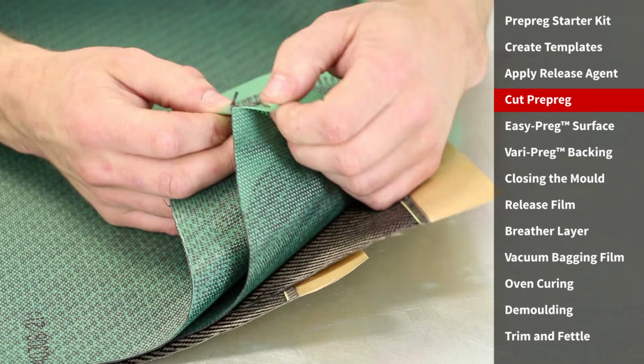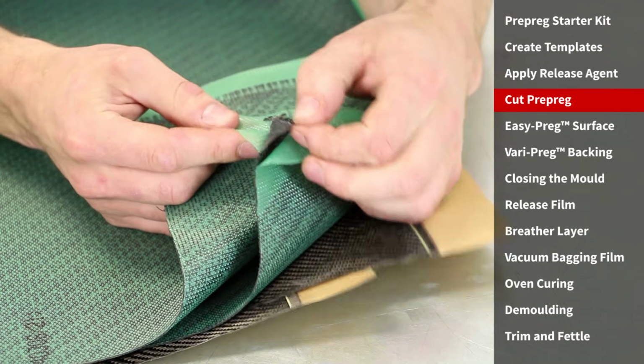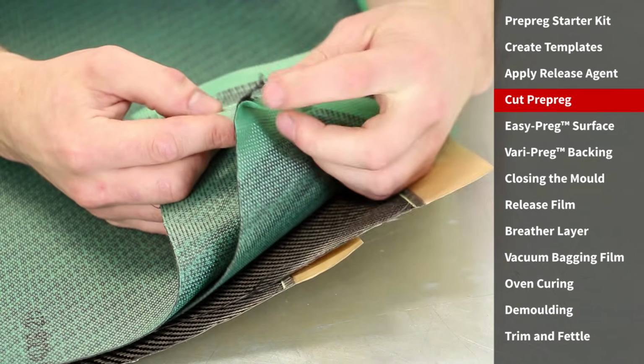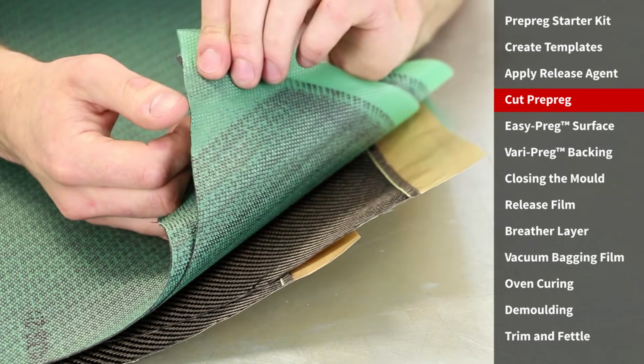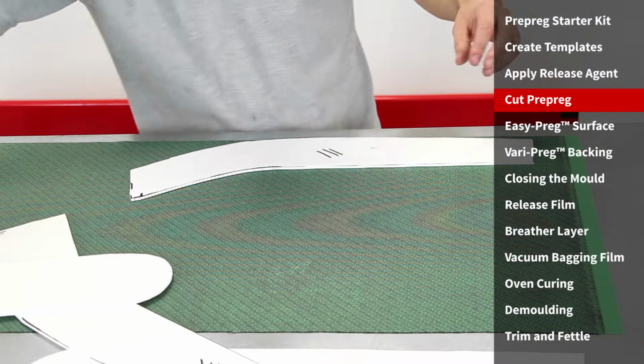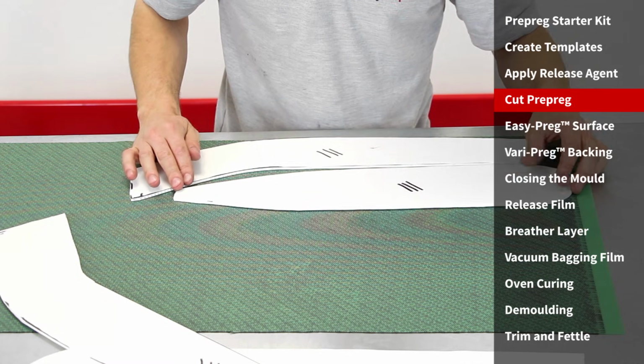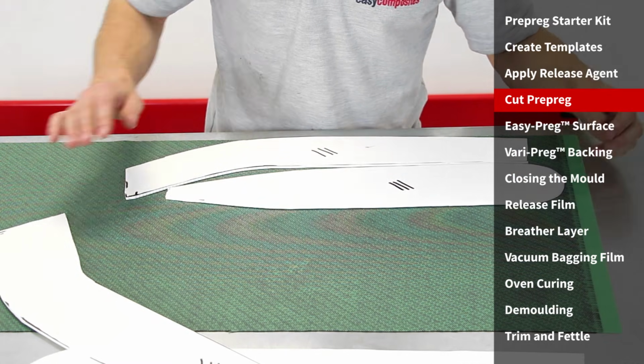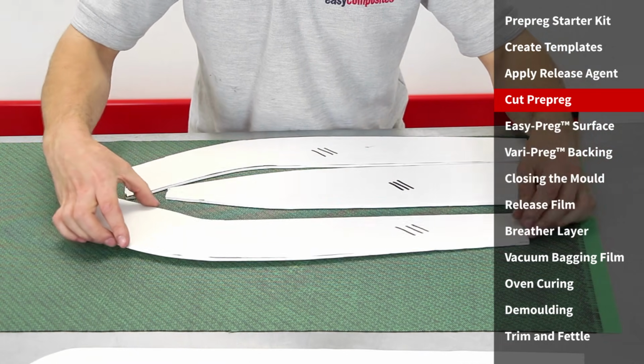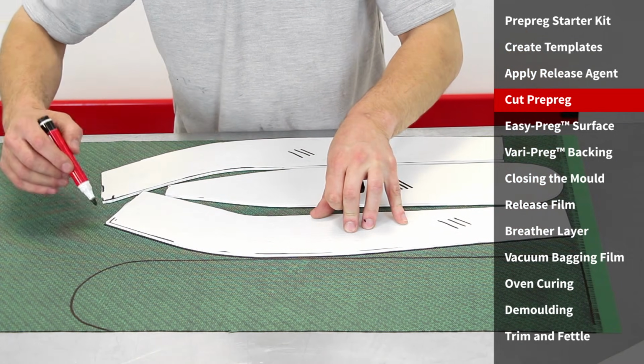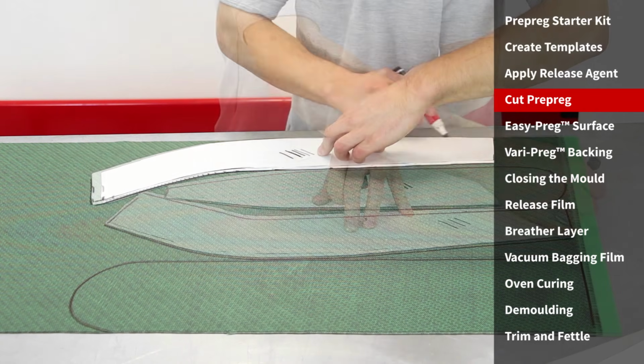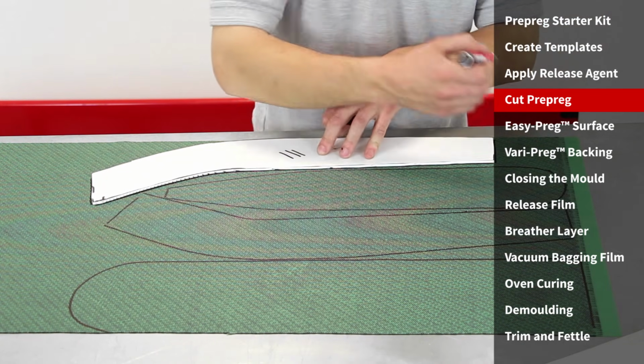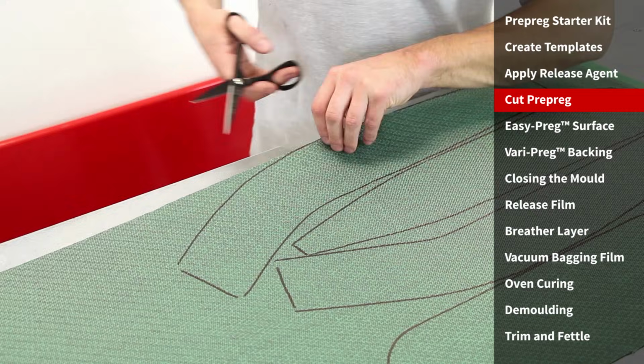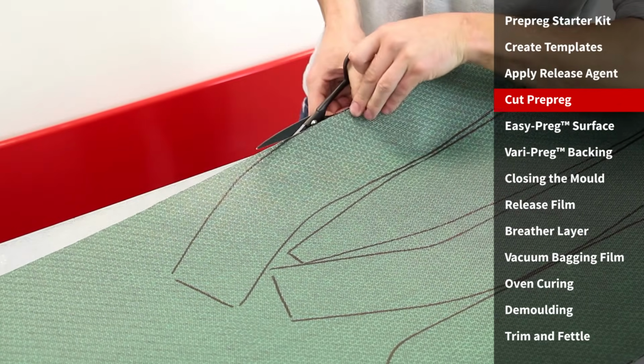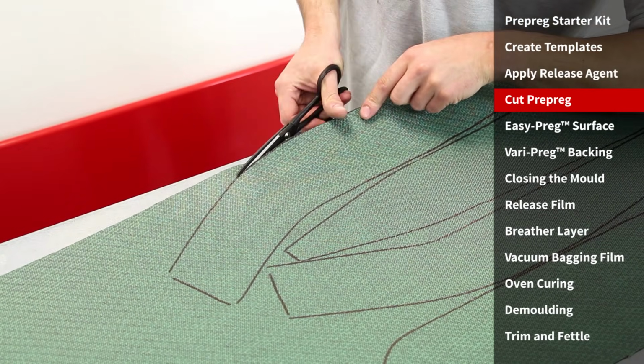The backing ply is much heavier material, made from a 430 gram cloth, and that can be identified by the fact it's got a plastic covering on both sides. You're looking to get these templates nested as tightly as you can, thus avoiding waste material. Cutting the prepreg is very straightforward as long as you've got a substantial pair of shears.